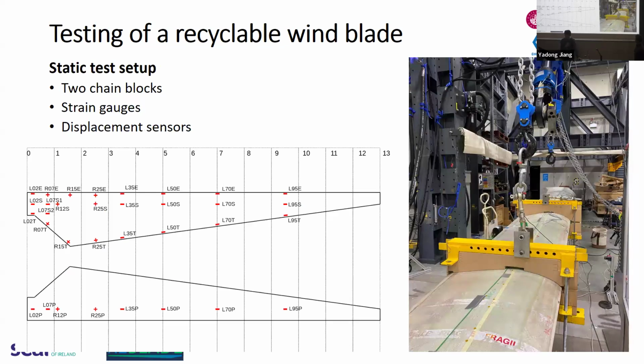Okay, so this one is a 30-meter blade, and it's far more complex than the demonstrator. And here we used a lot of strain gauges, as you can see here on the upper sides, lower sides, leading edge and trailing edge of the blade to measure its responses. And besides that, there are two load points to apply the load to simulate the wind load for the wind turbine blade.